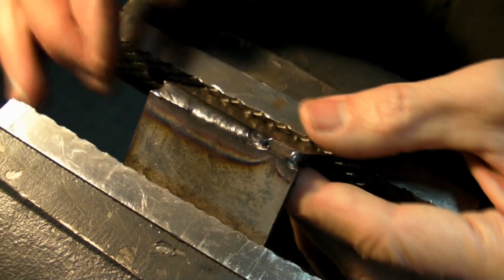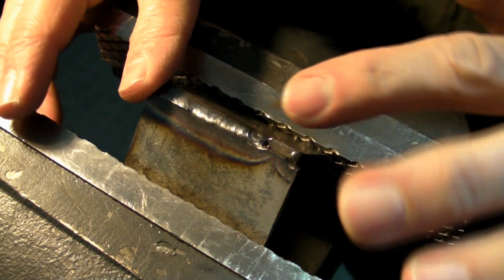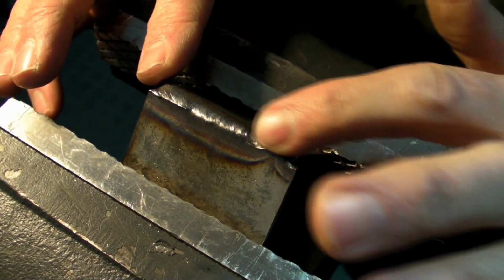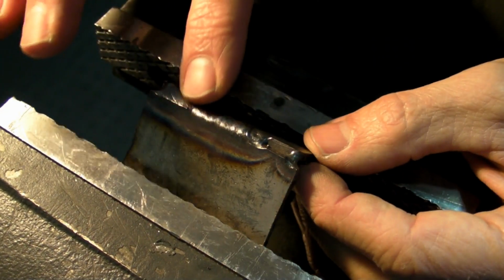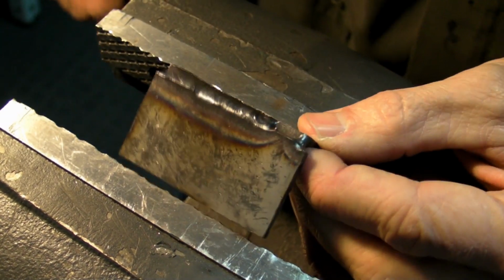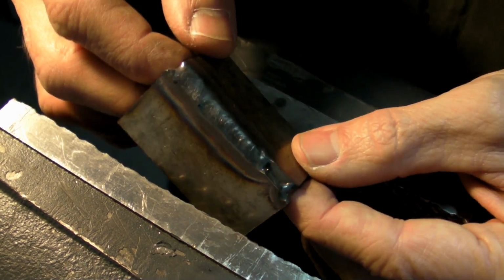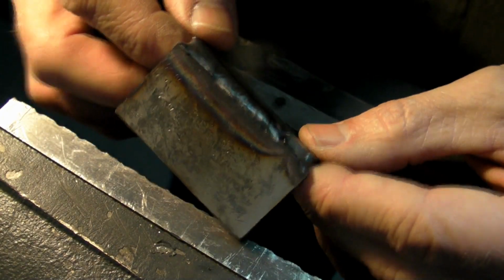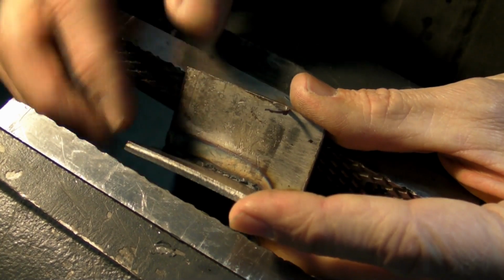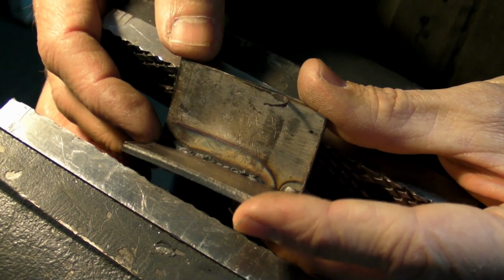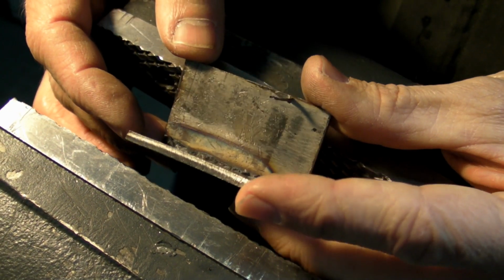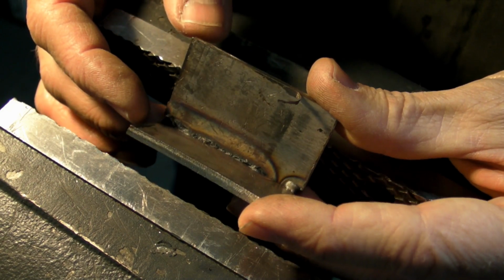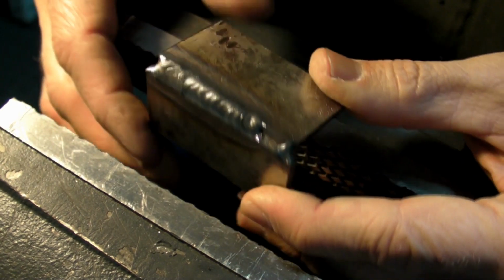All right, so the weld has cooled down nicely. I have a beginning and an end of the weld, so that will become part of the test. Got a nice wavy nature, so that looks pretty good. There's no collapsing of the outside of the weld, and a little bit of over penetration, but I can live with that for a 3mm plate. So this will be my setting for the rest of the boiler.